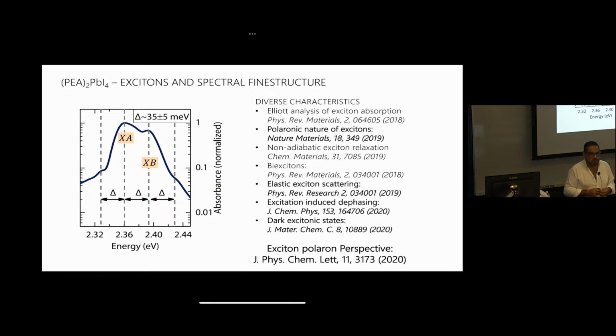And that seems to be something rather mesoscopic, because if I change iodide to bromide, you still get your 35 millielectron volts. The weights might change, the line shape details will slightly change, but it's about 35, 40 millielectron volts. You change lead to tin, you get about 35 millielectron volts. You change the phenylethylammonium ligand to something else, same thing. You put in 2 layers, 3, 4, 5 layers of lead iodide, 35, 40 millielectron volt line spacing. And so if you're a chemist, you think this really looks like something we really understand.